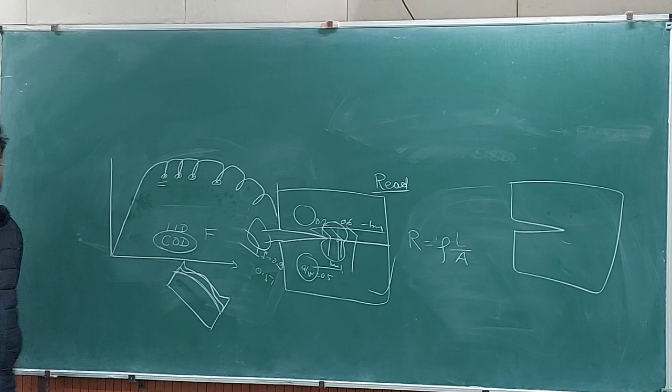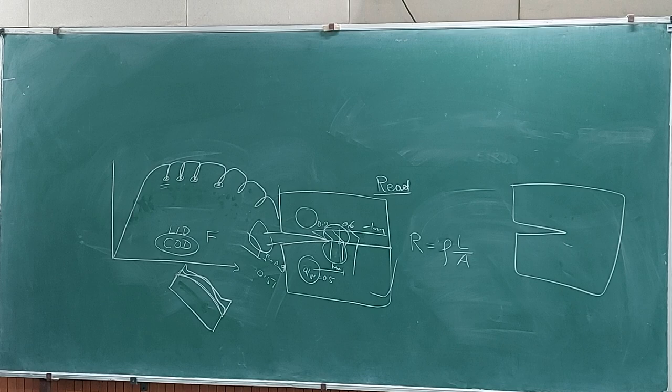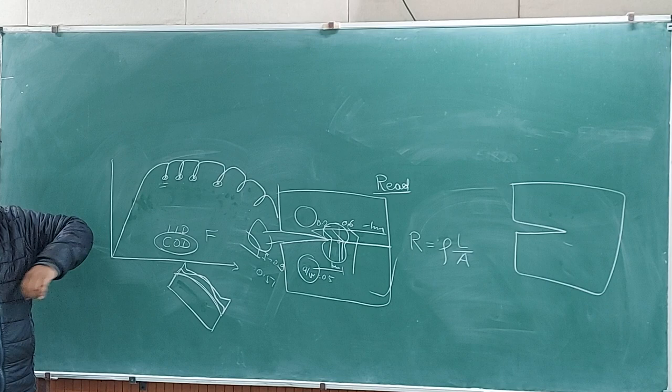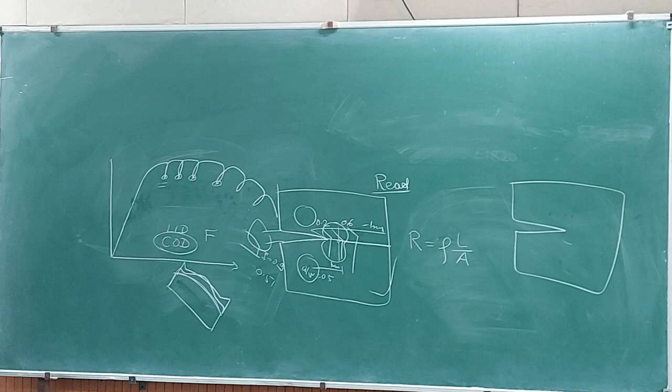But nevertheless, in the analysis, you can't really use n number of crack delta A values for one point calculation. At each point, you really need only one value. And that you are getting from the potential drop method. You are passing direct current, not alternating current. So that is called the direct current potential drop method of crack growth measurement, DCPD.